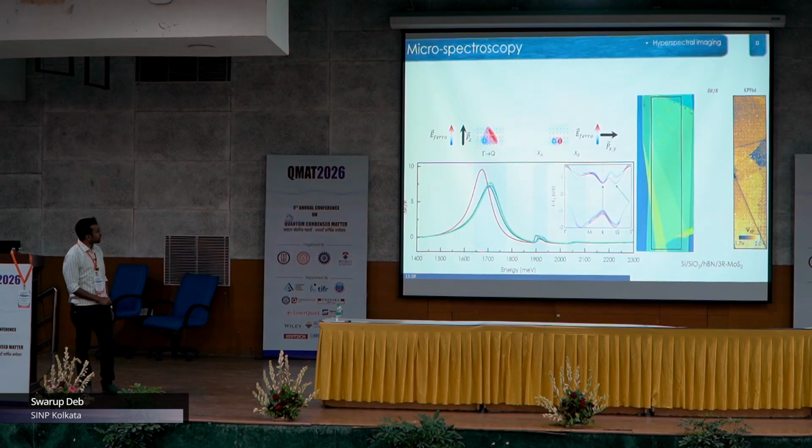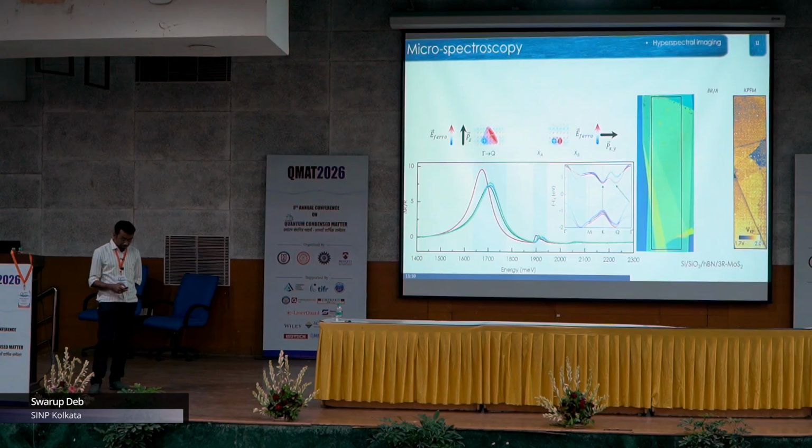On the other hand, we can actually probe this indirect transition by choosing the hBN thickness in a way, and then we can see what is known as the hybrid exciton, the gamma Q exciton. Over here the hole is confined to one of the layers, but the electron is distributed in the entire stack. Therefore, these excitons have both in plane and out of plane dipole moment.